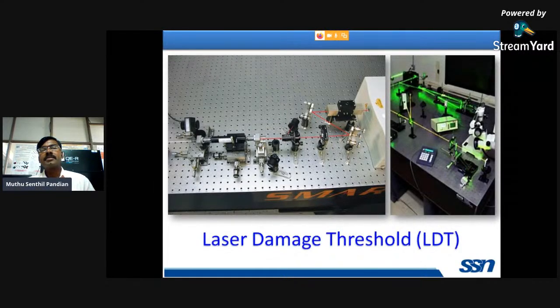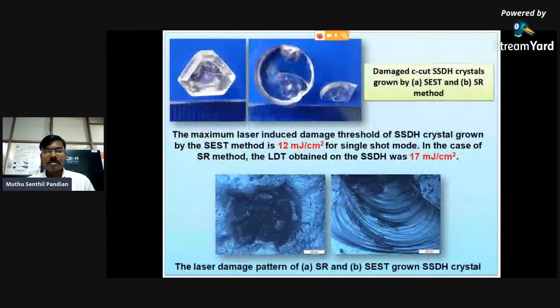So for laser application, one must know the laser damage threshold value. Under identical conditions, we have measured the laser damage threshold value. The maximum laser induced damage threshold of this SSDK, sodium sulfate iodide, that golden color crystal. This is for the conventional method. This is for the SR method. It is 12 millijoule per centimeter square in single shot mode for the conventional method. Under identical thickness, this is for the SR method. It is 17 millijoule per centimeter square.